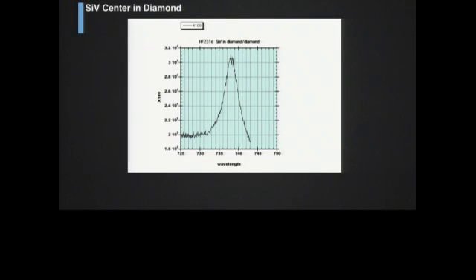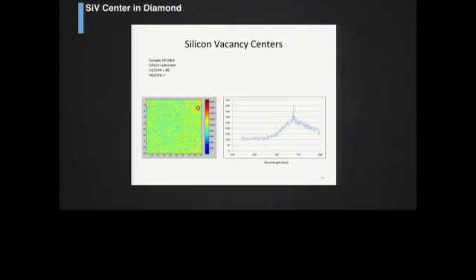We've also done fluorescence on the silicon vacancy center as well. This is the silicon vacancy center, and you notice how sharp it is. And because of the weak phonon coupling, you don't have the side bands that you had when you had the NV center. And we've also been able to isolate a single silicon vacancy, and you can see we do a scan across the entire wafer, we can identify a single silicon vacancy.